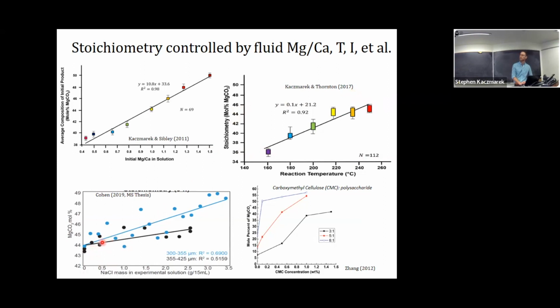You can also change the salinity of those fluids, where the more saline fluids correspond to a higher degree of magnesium in there. And other work has shown increase the amount of carbohydrates or polysaccharides in the fluid, and you get a higher degree of stoichiometry. So some key parameters that vary in nature: natural fluids vary in their temperatures, their chemical composition, salinity, and the amount of organic matter that's in them. And this all has a control on the dolomite stoichiometry.